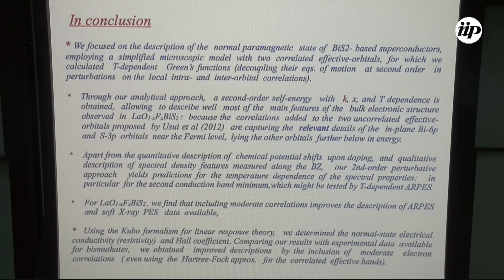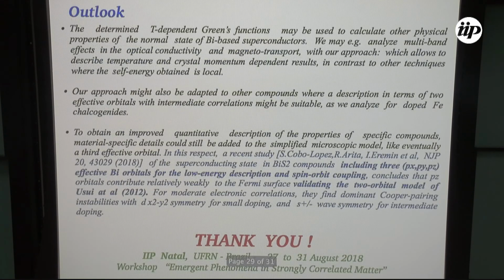And what we find is indeed that correlations are needed. Moderate correlations are the ones that improve the description. If you don't put them in, you have some problems. If you put them in too large, you also have problems. So it's nice that we are finding this. Our idea would be to continue looking at other properties. We have the Green functions. We can tune doping, temperature, etc. So there's a lot of work we can do.